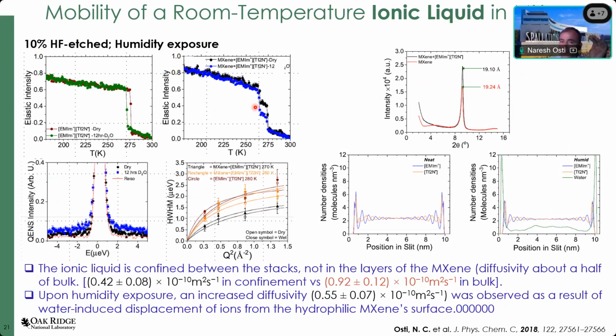Before looking at the confined system, we collected the elastic intensity as a function of temperature for the bulk ionic liquid. As you can see, there's a strong decrease in the intensity somewhere around 275 Kelvin. This is because of the freezing-melting transition, which is the universal thing that you can see in bulk material, bulk liquid solvent. Once you expose it to D2O vapor, you can see a small decrease in the transition temperature because the water molecules disrupt some of the hydrogen bonding network present in the ionic liquid system.